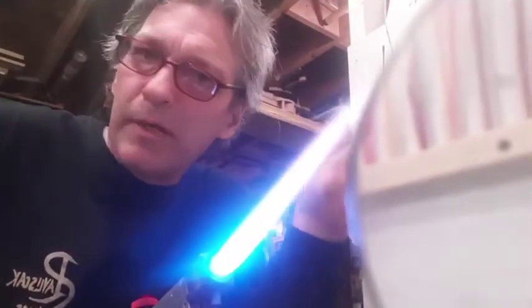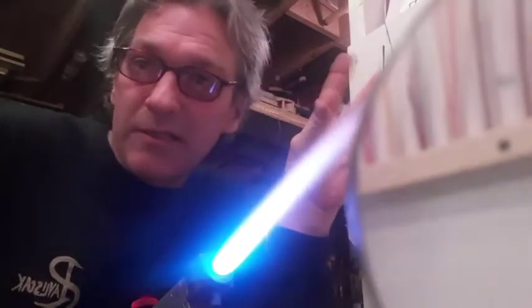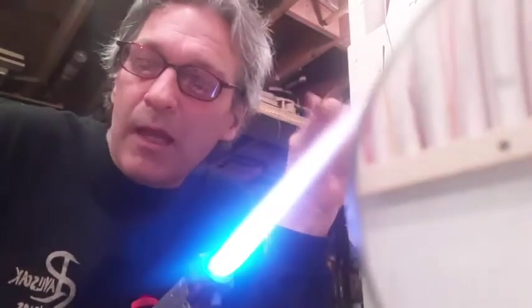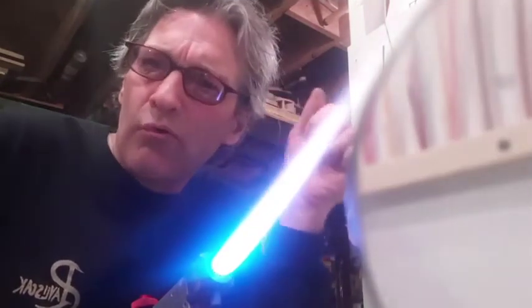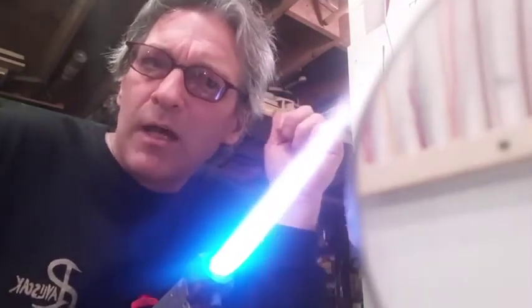All right, so the marble, let me punch these. The marble will stay in the annealer. That's a small marble, so it really only needs to stay in there for like an hour. And then if it was an inch or bigger, I would bump it up to 2 hours at least in there at 960 to 980. And then I would ramp it down over 2 hours. For this one, it can stay there for an hour, and then I'll ramp it down over an hour and a half.